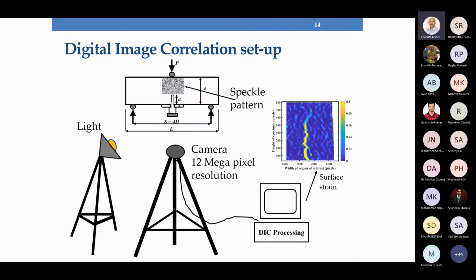For digital imaging, we have used a black spray paint on the surface of the concrete beam to get a speckle pattern, and using a 12 megapixel resolution camera mounted on a tripod with a remote, we have taken continuous digital images, or we can even take a video. Later, using a correlation algorithm, we can analyze these pictures and determine the displacements and strains on the surface of the material. So the idea was to get all the surface information using digital imaging, and all the information from within the material, the micro cracks, especially the events which we call micro cracks.